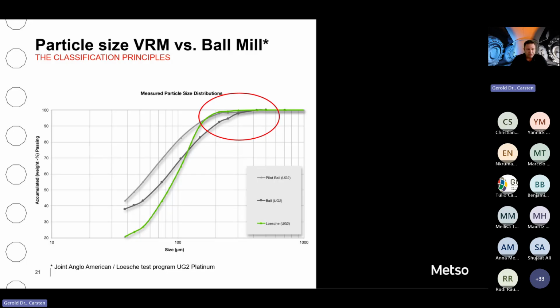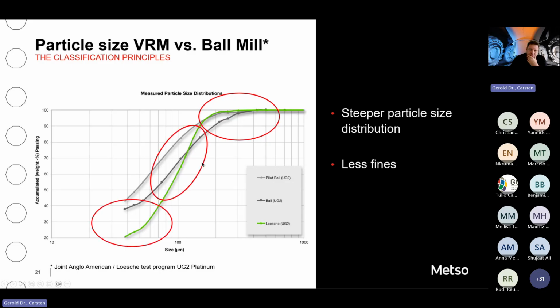This is the example of a joint work we did with Anglo American on a UG2 platinum ore. The Bond work index is around 24. And what is compared here is in green the product particle size of a lab VRM in comparison to ball milling. And the black curve is the industrial ball mill, the gray one is the laboratory. And what you can see is we have a steeper particle size distribution in total. We have less fines in here, and we have less coarse.